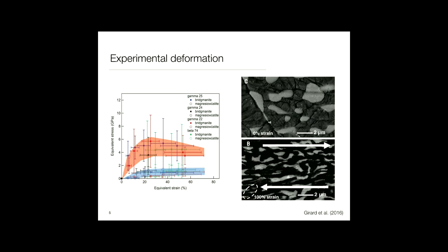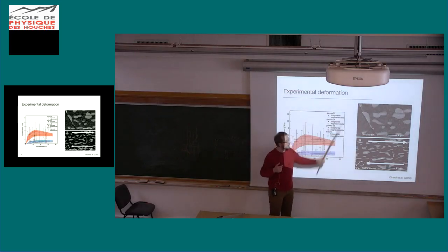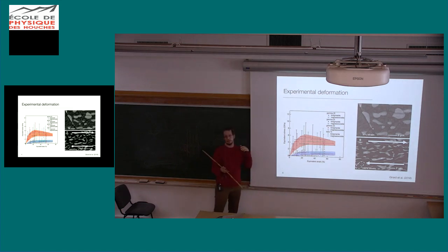when you look here at this paper by Girard et al., where they had this bridgmanite and ferropericlase mixture and deformed it in simple shear, they found that in the ferropericlase or magnesiowüstite, which depends a bit on your iron or magnesium content, you have different stresses in both materials because they have different strength.